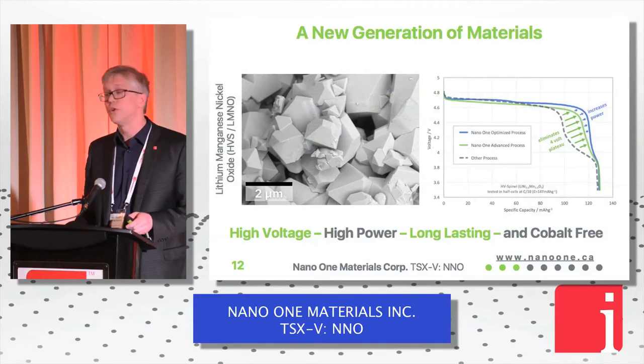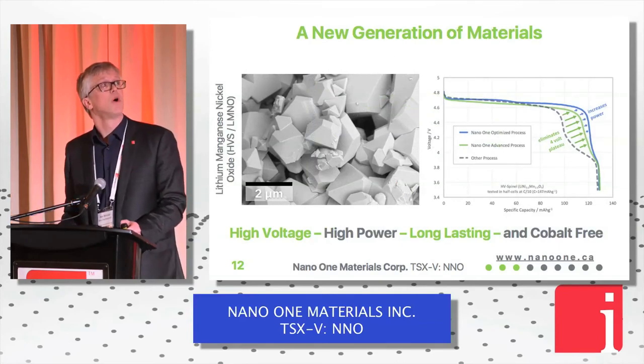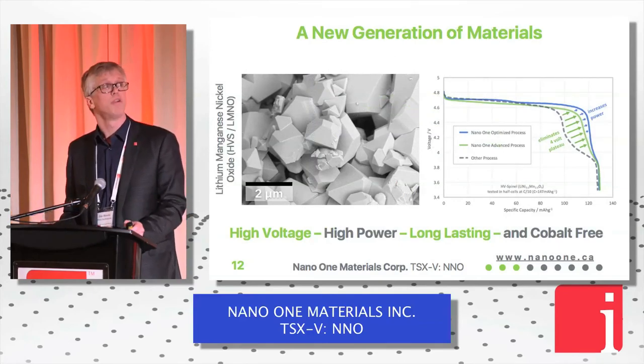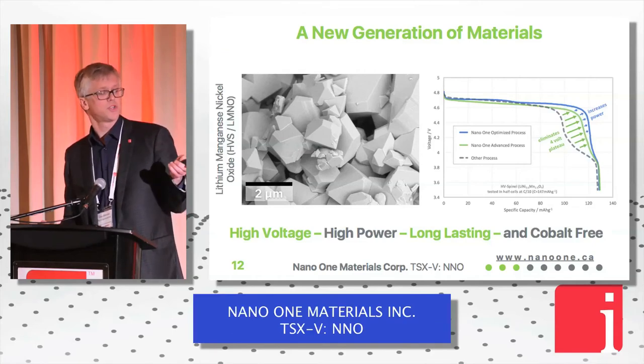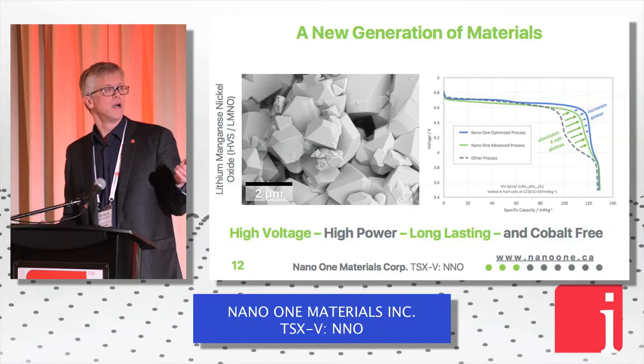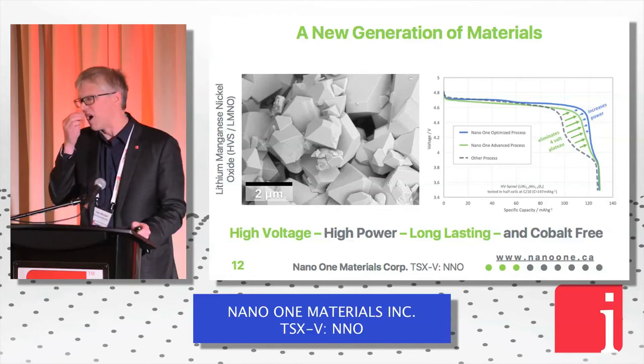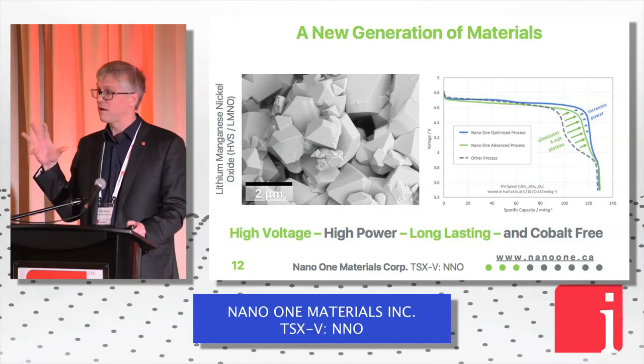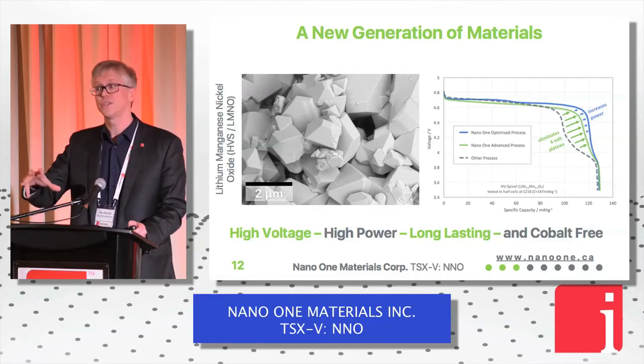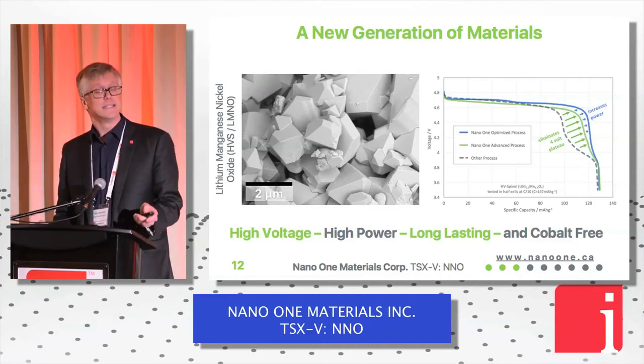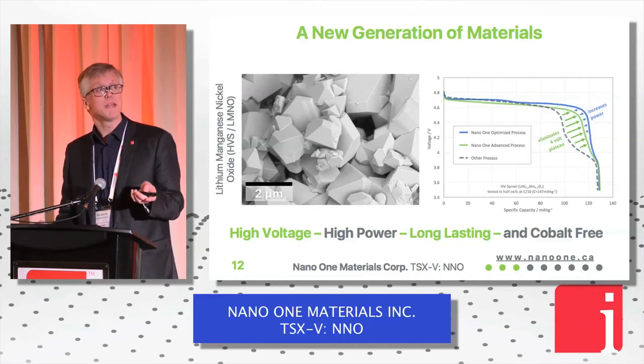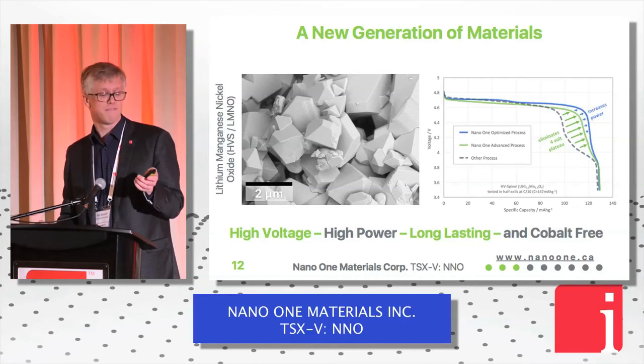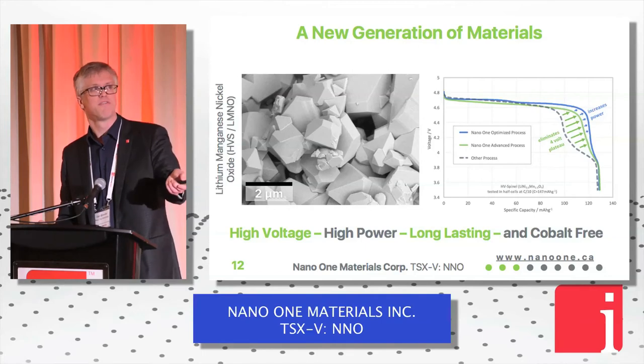Another material that I alluded to earlier today is what we call our high voltage spinel or cobalt free material. So this has manganese and nickel in it, but there's no cobalt. And you can see the structure of the material looks very different. It's what we call a high power material, so you're able to charge this material very quickly and discharge it very quickly. And we've made some very significant improvements in the way this material is made. In fact, there isn't really anyone out there that's able to make the materials as effectively as we can.